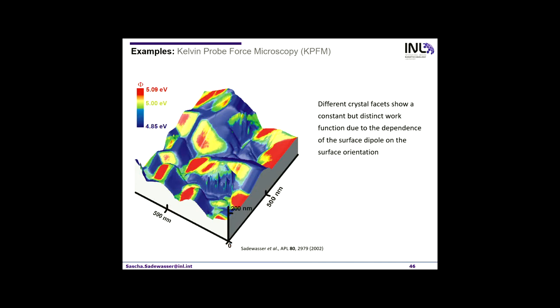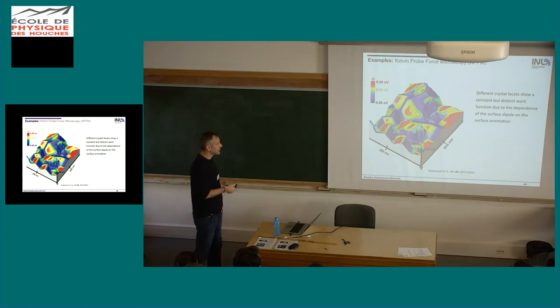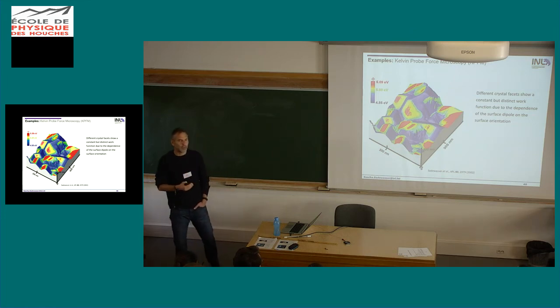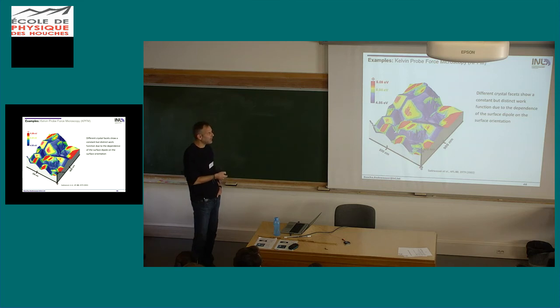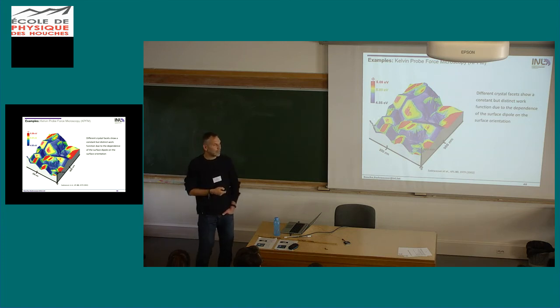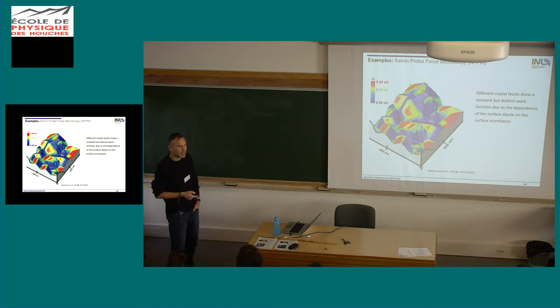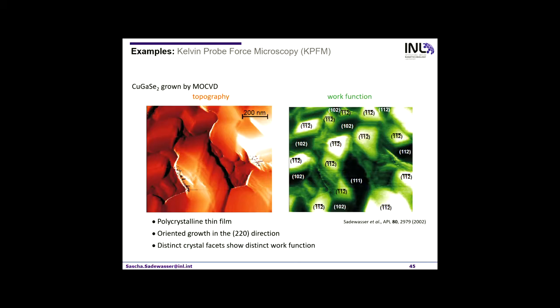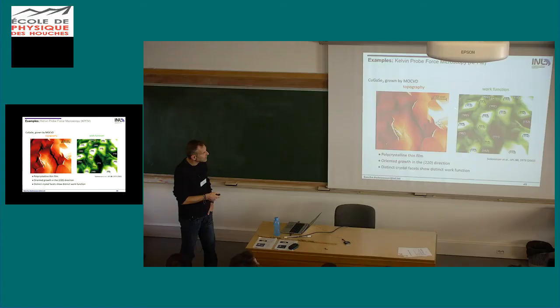So the reason is that, of course, why do you get different work functions? On one hand, you can change the doping, but of course that cannot happen in the same grain. We cannot have the same grain with two different facets and different dopings. That's not possible. So the reason is that the electron affinity is changed, and the electron affinity includes the surface dipole, and that surface dipole depends on the atomic termination of the surface. So again, here this is selenium terminated, so selenium is the anion.